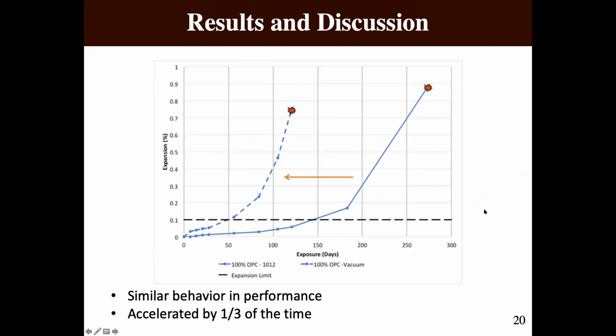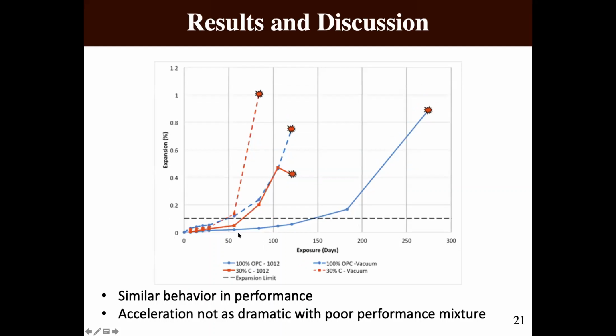And so now when you look at the vacuum saturation system, clearly when you have the control in comparison to the 10-12, you have a dramatic increase in terms of expansion, right? And dramatic acceleration in the rate of expansion. Whereas this didn't pass the expansion limit until about 6 months, we reached that expansion limit in as little as 60 days, or about 8 weeks or so, with the vacuum saturation. So about 1/3 of the time.